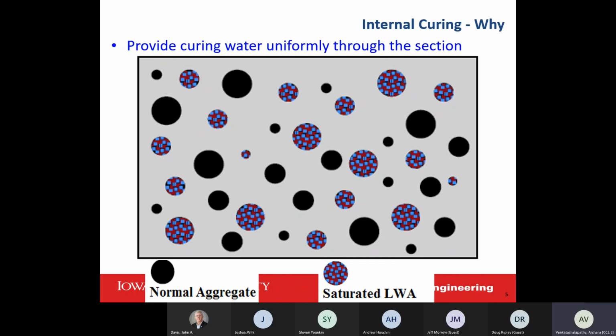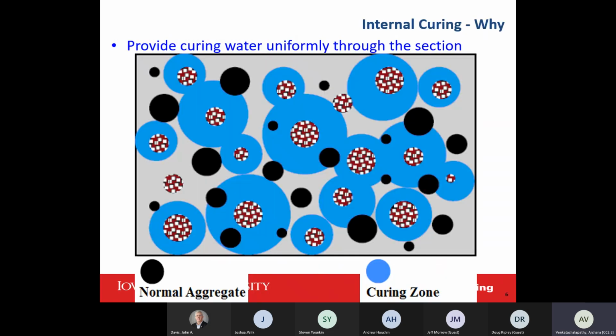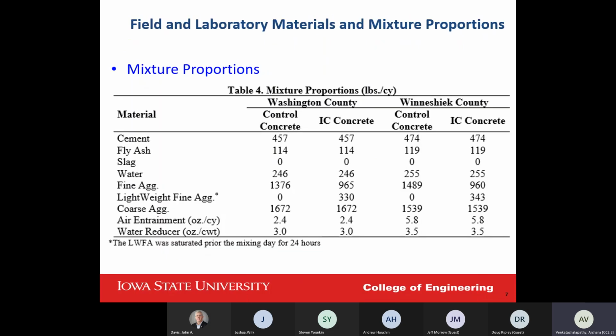So you don't want to change the water cement ratio in the beginning, but after 24 hours the hydration starts going on and the concrete starts getting drier. Then it starts sucking the water out of the aggregate, and that's how the hydration keeps going on even after around a month. The only thing that has been changed in our mix design was the amount of fine aggregate. So we tried to keep everything identical except the fine aggregate, where we start using lightweight fine aggregate volume-wise.